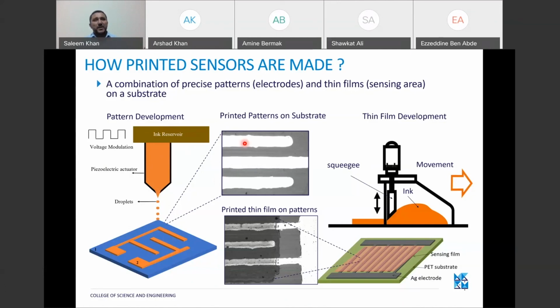These are the printed patterns. This is silver lines which are printed on PET substrates. And there are different steps that we do before and after, like pre-treatment and post-treatments. And these are the annealed structures that we achieve finally after doing our printing.